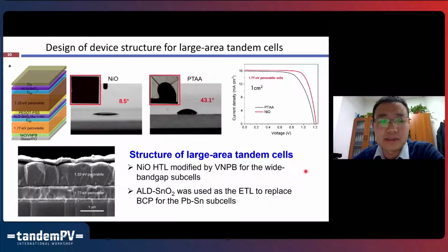The first issue we encountered is that when we typically use hole transport layers such as PTAA, we found wetting is a big issue for making large area tandem devices. So later we adopted a nickel oxide nanocrystal film as the hole transport layer, because this nickel oxide film has a very good wetting ability, and also reduces the interfacial recombination losses. We also add a thin layer of VNPB for defect passivation. With this design, we can also much improve the efficiency of the top wide bandgap subcell.